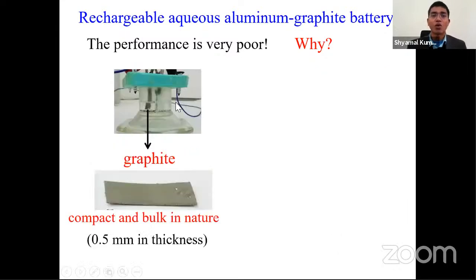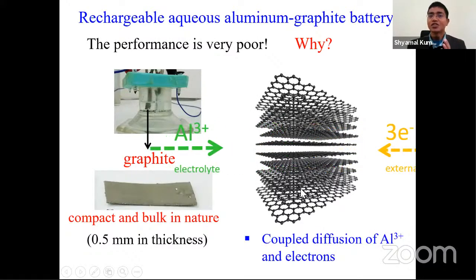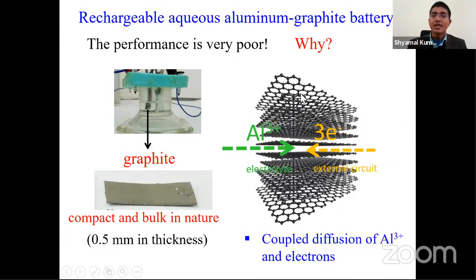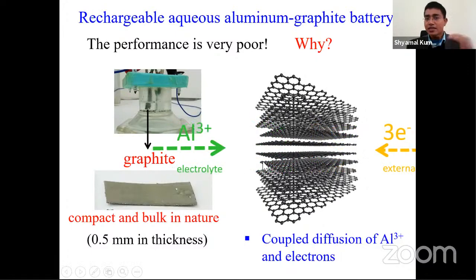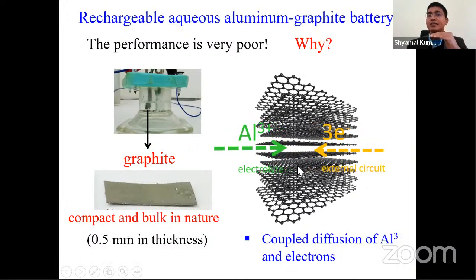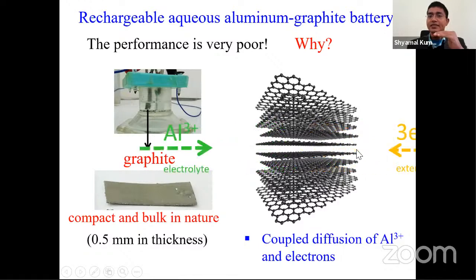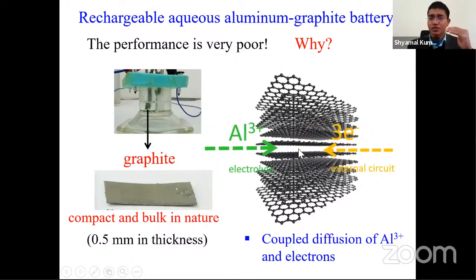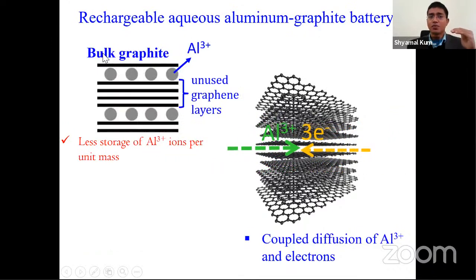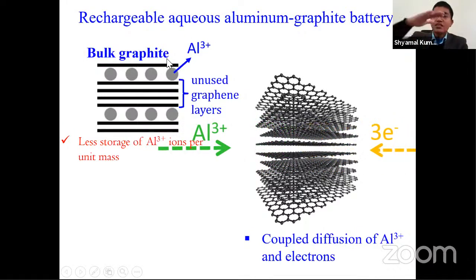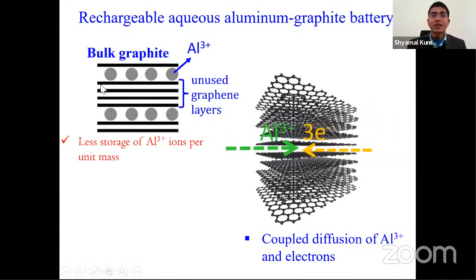Let us first discuss the why. Whatever graphite we use in our cell is very compact and bulky in nature. We use 0.5 mm thick graphite. Fundamentally, this piece of graphite has certain graphene layers, and aluminum ions from the electrolyte diffuse inside these graphene layers, and electrons from the external circuit travel to the graphene. This is a coupled process. So if we use bulk graphite, there are a large number of graphene sheets, and not all the graphene sheets can be used by aluminum ions. There are a few unused graphene layers. That is why we see less storage of aluminum ions.